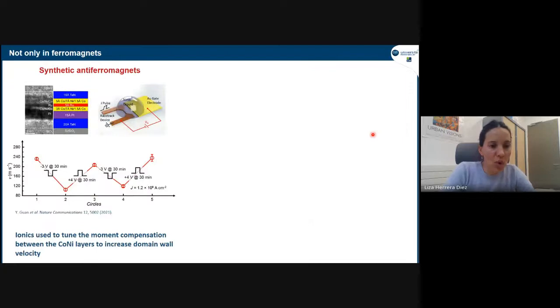But this is not limited to ferromagnets. People have been investigating magneto-ionics in other types of magnetic systems. What is really interesting is what has been done with synthetic anti-ferromagnets. Actually, from this same group, before they did this work on magneto-ionics, they could show that domain wall velocities could increase a lot if the magnetic moment of the domain wall could be compensated. So what they did was to build a stack like this one, that is anti-ferromagnetically coupled. They have a top layer where they were observing the domain wall motion, and then a ruthenium layer which couples it anti-ferromagnetically with a bottom layer.